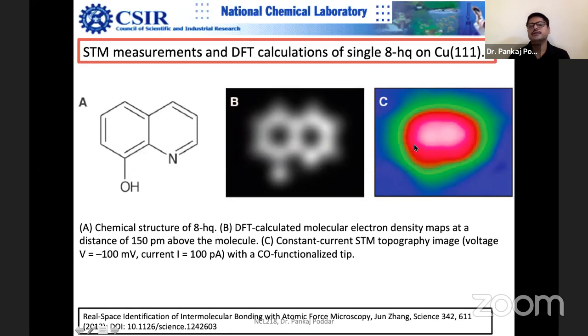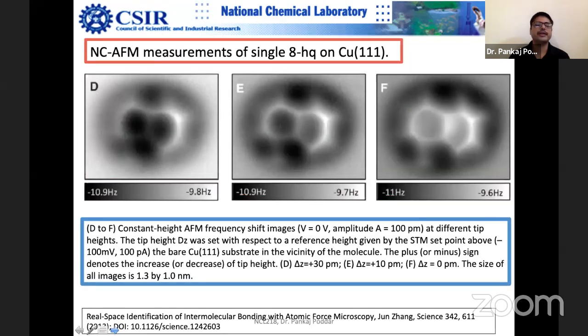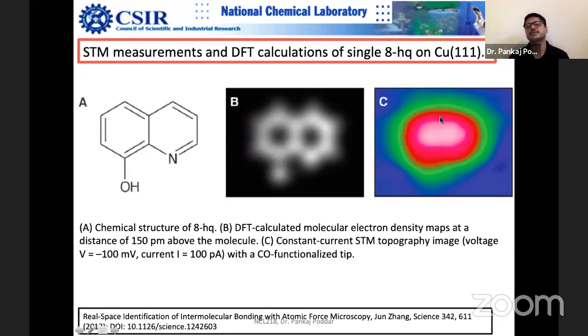You are not able to distinguish between the two rings because they probably form a big ring of current. In STM, basically you are measuring the current. Everywhere here you will measure it because of the pi electrons. They are itinerant electrons. Because the two rings are joined together, you will see something like this. But if you do the same thing using AFM, which is not dependent upon current, then in current measurements you have a problem. You may not see the rings separately.